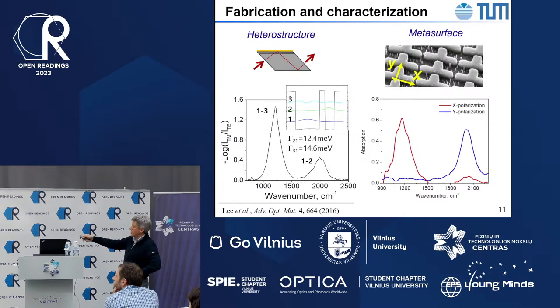We confirm that these states are where we designed them to be, and then we process it into the metasurface with antennas. We could probe the resonances of the antennas for X-polarized light. It's this long resonance at long wavelengths, and for the short wavelength, for the output frequency, it's another resonance. It's along the Y direction, so the resonances are at the right place for the input and output.